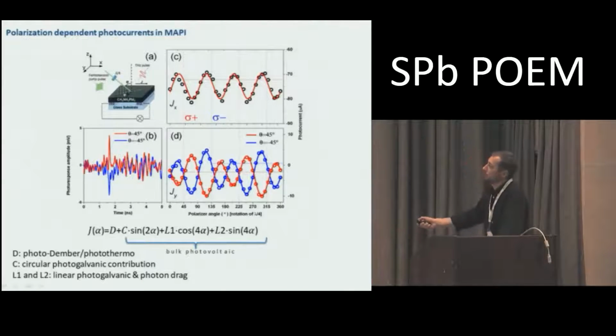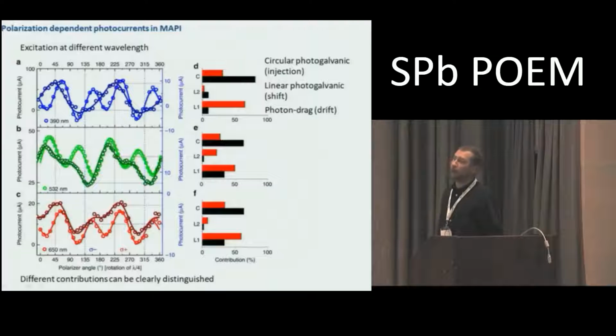So the overall photocurrent response can be described in this way, where the D term is a photo-Dember effect or photothermoelectric effect, which is polarization insensitive, and these coefficients correspond to circular and linear photogalvanic effect and photon drag effect, which we are actually interested in. We apply different wavelengths to excite these photocurrents, and can clearly see that the contribution of different types of currents strongly depends not only on polarization but also on wavelength.